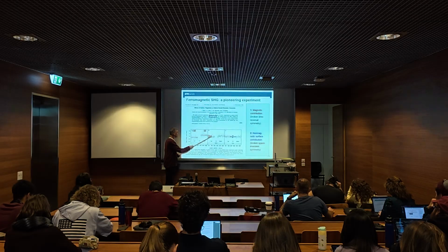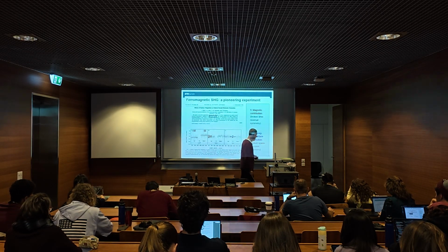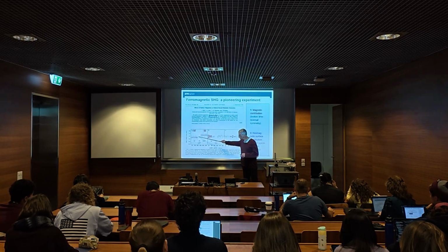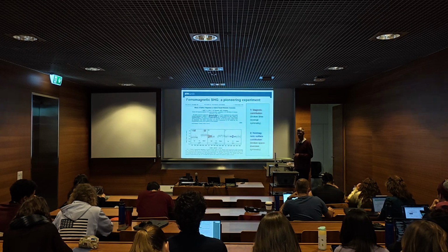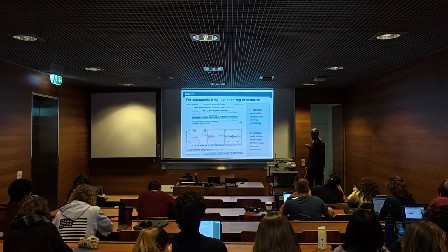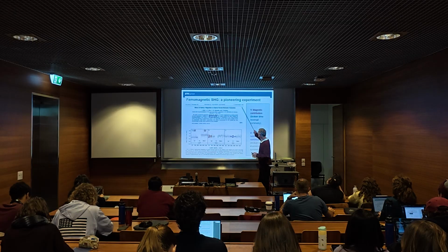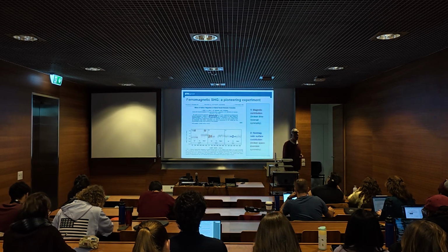And that difference goes away when you oxidize your surface, so that the magnetization is gone. So you have a background contribution from the surface, and this splitting here, this is all due to the magnetization. So that was about the first time, not the very first experiment, it was the first very convincing experiment in 1991 where they showed that frequency doubling can see magnetism.